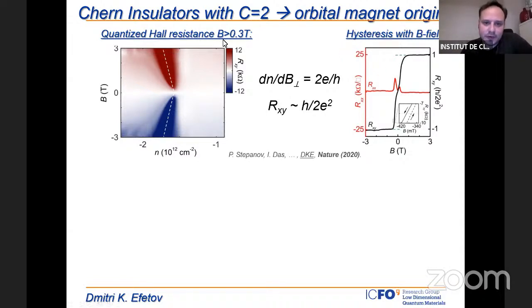Just to give an example, this is a typical measurement of one of those Chern insulators. What you see here is this point here. This is minus a filling of the valence band, so this is a filling of -2. And you can see that, depending on the magnetic field direction, we really get these perfectly quantized regions. If you take a cross section along this line here, this measurement on the right, we see that Rxy is quantized to h over 2e squared. And again, this is a filling factor of 2, so this is all consistent. And Rxx is almost 0.